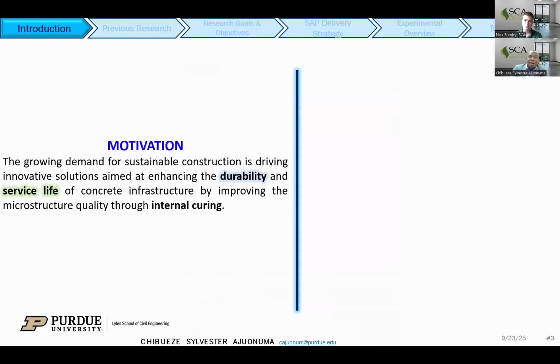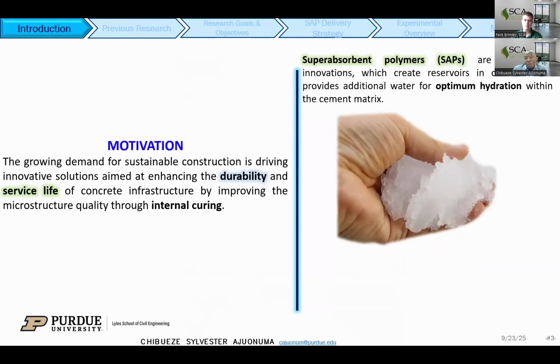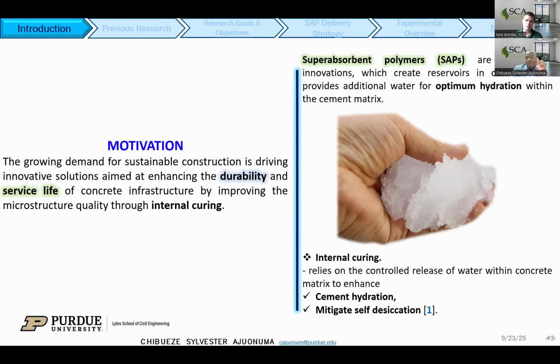We know that there's a growing demand for sustainable construction, which is driving innovative solutions aimed at enhancing both the durability and service life of concrete structures. And one of those can be attained by improving the quality of the microstructure of concrete, and by curing. Further, superabsorbent polymer, which is known as SAP, comes in handy as one of such innovative materials, which tends to create reservoirs within the concrete that help to provide additional water, additional moisture, within the cementitious matrix that improves the hydration of concrete. And we found that internal curing relies on the controlled release of water within the concrete mixes. This helps to improve hydration and mitigates self-desiccation in concrete structures.